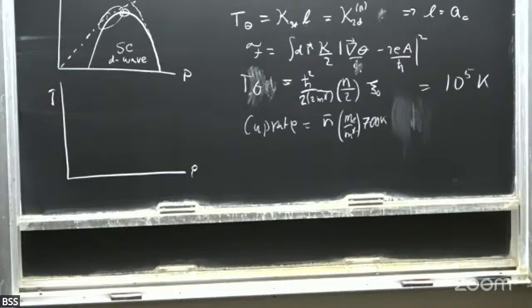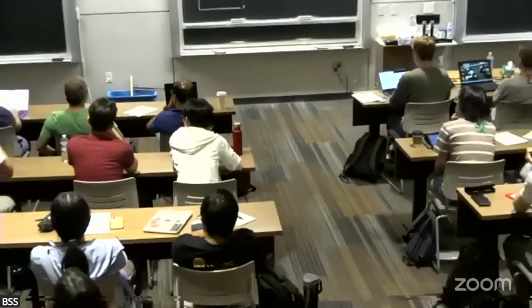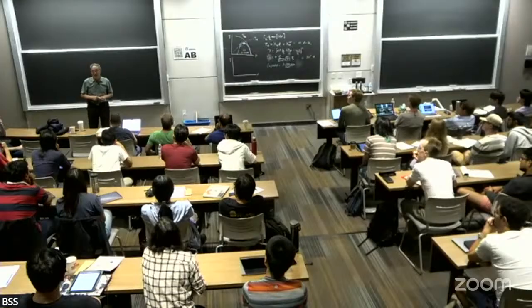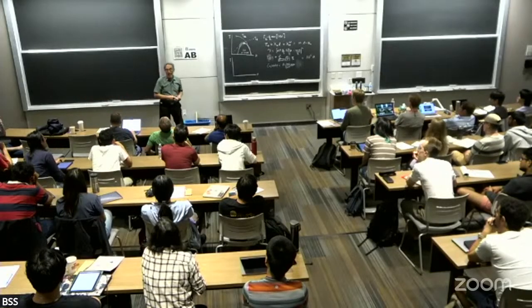Sorry, before you go on, could you say again exactly what being able to see many decades of 3D XY behavior near the phase transition means? Isn't that just because of a short coherence length? So this is interesting. Usually you would estimate the Ginzburg parameter. If you estimate the Ginzburg parameter, actually, it's quite small, even in the cuprates. This really upset people who were experts in superconductivity because the Ginzburg parameter comes out to be, I can't remember, a 30th or something like that. So you would have expected rather small fluctuation regimes.